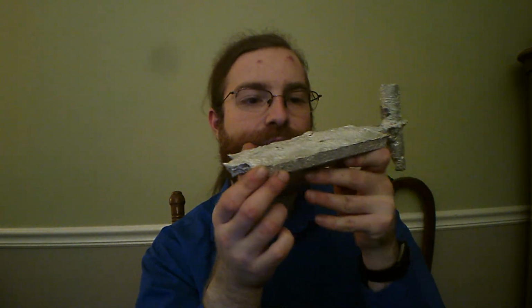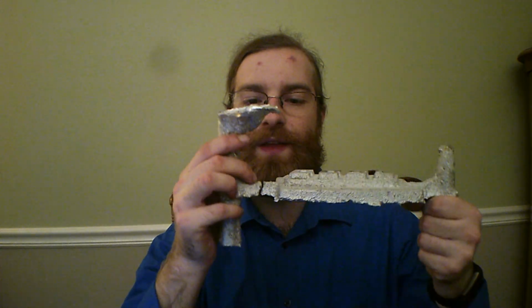Also, the back surface of this thing is the opposite of flat. It contours around itself, and the reason for that was I rammed up an empty drag first, that iteration, put this down on the drag, and then rammed the cope over it, and so this was in the cope half. So the top of the pour was over here where the sprue used to be, which I knocked off in the hey, this is brittle demonstration. That fit right there.